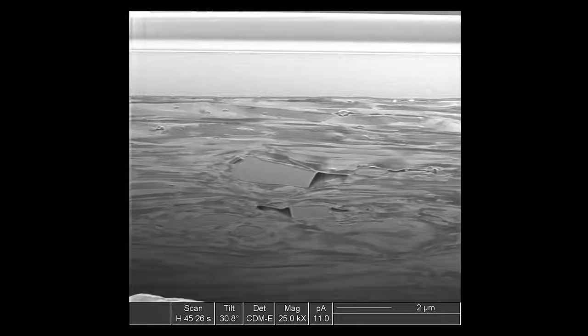So this is an example of an aluminum plate which has been stretched out to form a vessel, in this case a soda can, and it has some inclusions inside of it. And you can tell that it's been stretched out during processing because all the grains are very long and thin, as opposed to their more normal equiaxed shape. So you can tell the direction in which the sample was stretched, and you can also see that these hard inclusions, which are not able to flow and bend like the rest of the metal, leave voids around them, which could of course lead to failure if you had enough of those in a single location.